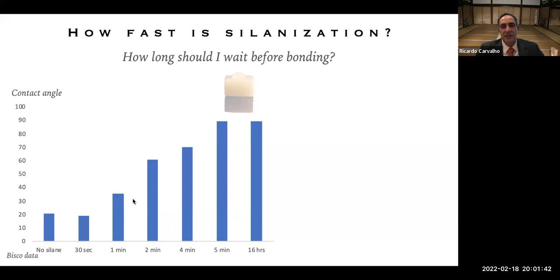As you leave it longer, the contact angle starts increasing, which is a normal thing to happen. It's a chemical reaction, it takes time. The more time you allow, the better the chemical reaction. But after 5 minutes, up to 16 hours, there was no difference, which indicates that after 5 minutes the surface is probably saturated in terms of silanization. That's really important to understand, because sometimes people quickly apply the ceramic primer on the surface and apply the adhesive directly without allowing proper time for silanization to occur.